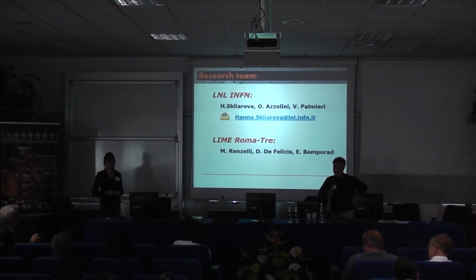So the question is where the porosity comes from, because the most trivial statement that Anna says is, I just tilt the magnetron and the substrate, I put the substrate up and I have less porosity. But our system is perfectly clean. Our target is 250 RRR. Where does it come from? What we suspect is that there are microparticles that, from the plasma at a certain regime, detach from the cathode and go onto the surface. And this is something that is not seen in the literature.